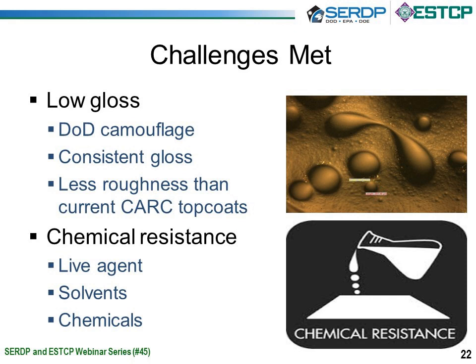So our approach was successful. We were able to get the low gloss needed for chemical agent resistant coating. So on the right here, we basically have a depiction of what we were able to produce with resin systems. So much like the ideal depiction in the cartoon, there are two resins on the right, and we basically have a domain, and we have a continuous film. So we have one resin system inside the other. This would be a low gloss coating in a clear coating.